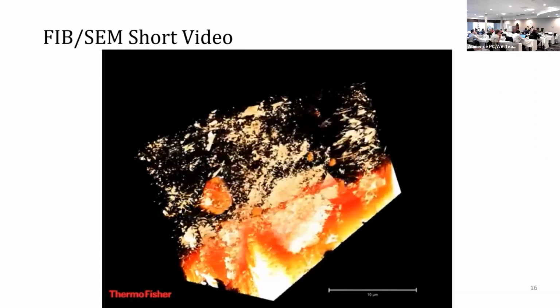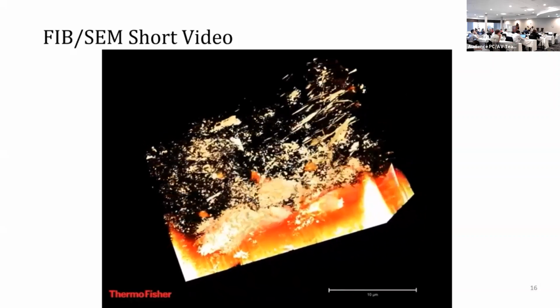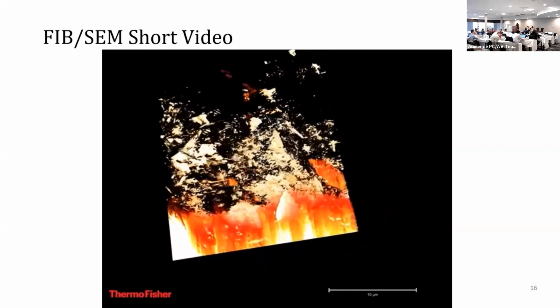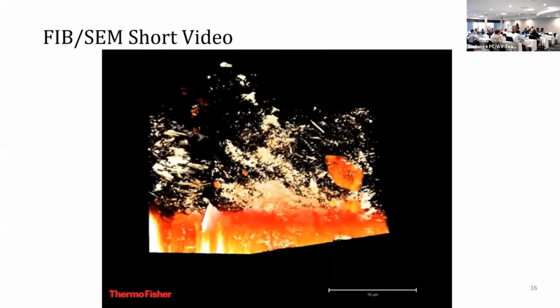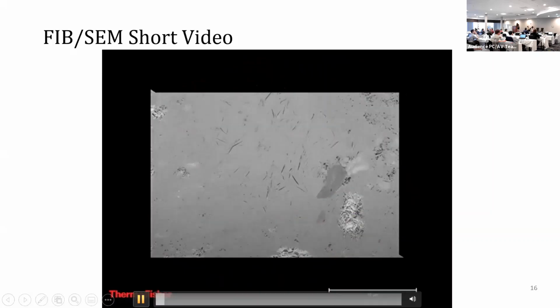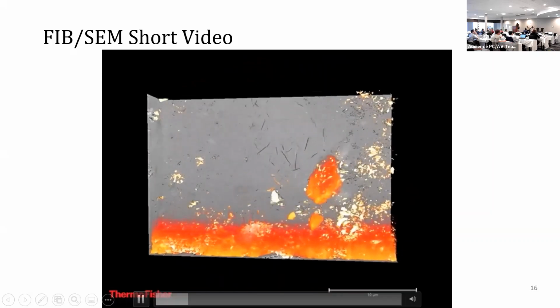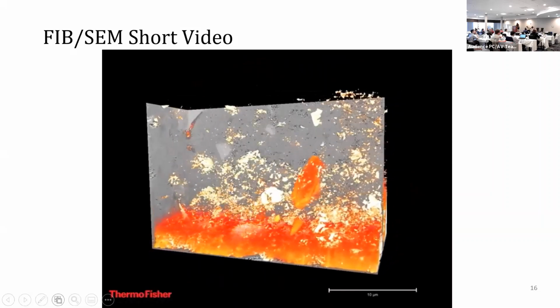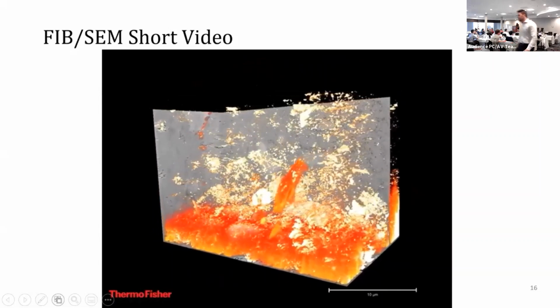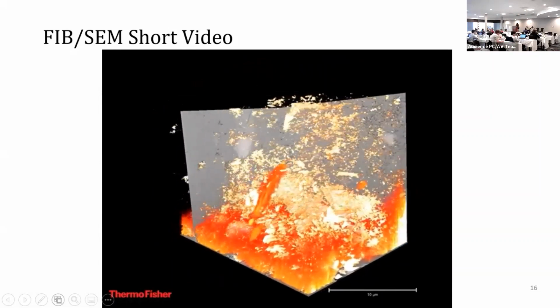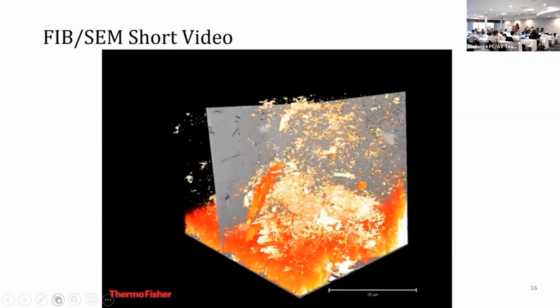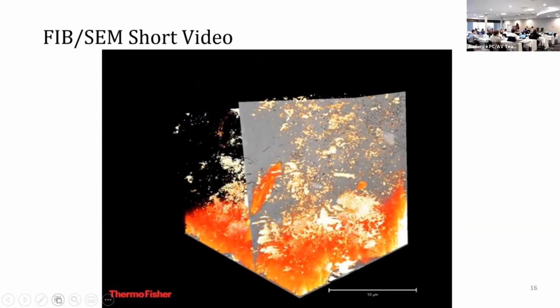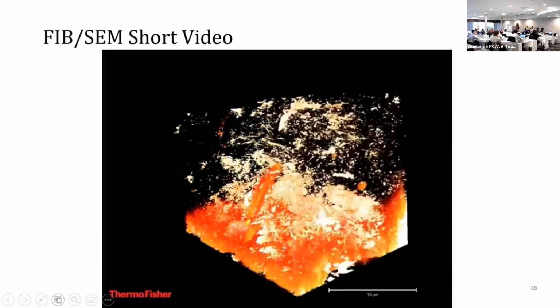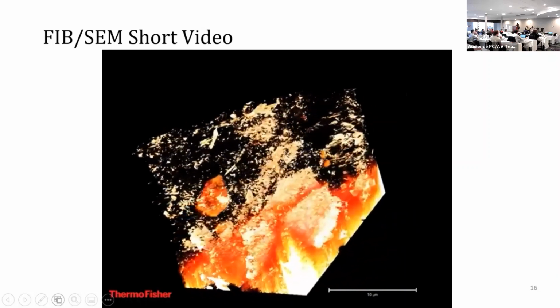That's the scale you need to be in if you want to look at particles that small, and you want to look at the calcium silicate hydrates, because they're really at that sub-micron scale. I'm going to play this one more time. If you look at these elongated black shapes, those are graphene nanoplatelets. Although this is still a little bit preliminary, this FIB-SEM is supporting our hypothesis that I showed earlier.